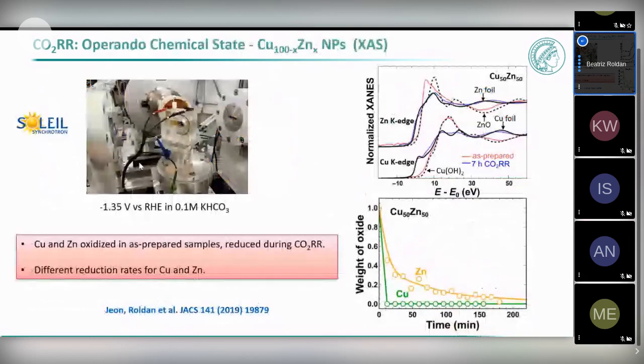So here we are at the synchrotron. Again, we are using X-ray absorption spectroscopy, and we are looking at our catalyst as prepared. We can look at both components, the zinc component and the copper component. And as prepared, our catalyst in red looks oxidized in zinc and in copper. But then under reaction conditions, you see the clear decomposition. Here in blue is the copper oxide, and here also. So this is zinc oxide, this is copper oxide, but the rate of reduction of the zinc component and copper component is not the same. So if you look at the weight of the oxide here, within the first couple of minutes, the copper is completely reduced very quickly, while the zinc oxide is reducing more slowly.